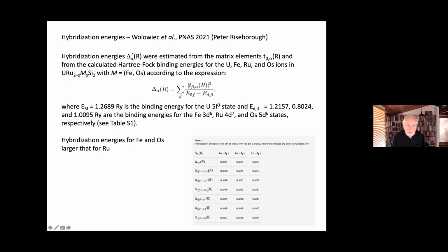And these are just some comments about the calculations of the hybridization energies. They depend upon the matrix element associated with the electronic orbitals due to uranium and these transition metals that are relevant. And then there's also a binding energy that appears in the denominator. And it turns out that these binding energies are lower for ruthenium due to its electronic structure. And so this gives rise to a reduction of the hybridization energy relative to iron and osmium. And so as you substitute them in for ruthenium, this increases the hybridization. And so they behave similarly in driving the transition from the hidden order phase to the large moment antiferromagnetic phase.